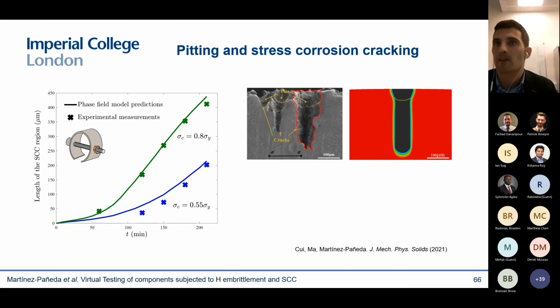At the end of the day, experiments are the ultimate judge, and we always make sure that all our model predictions deliver a good agreement with experiments. Here you can see the length of the corrosion damage region versus time, and these are for 2 experiments done at a different load. And you can see that we get a very good agreement with both, with no fitting parameters. Here we focus on modeling only one pit, but you can model multiple pits, as I've shown you before. And this is on the same scale, and you can see that we get a good agreement in terms of the main defect shape and length.